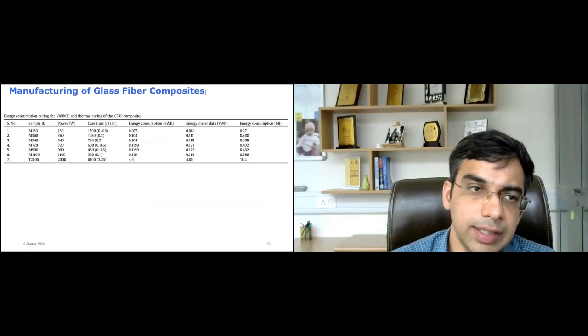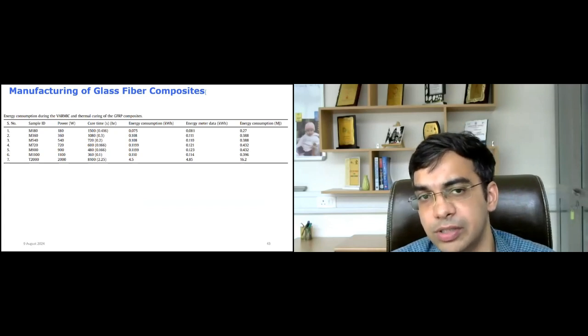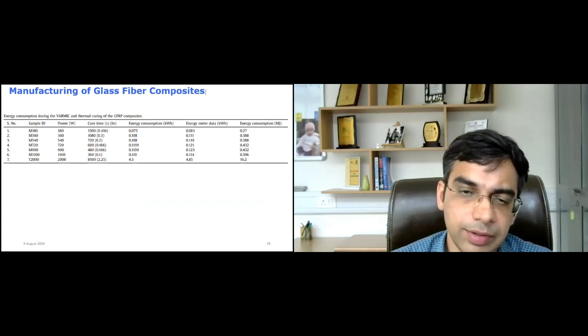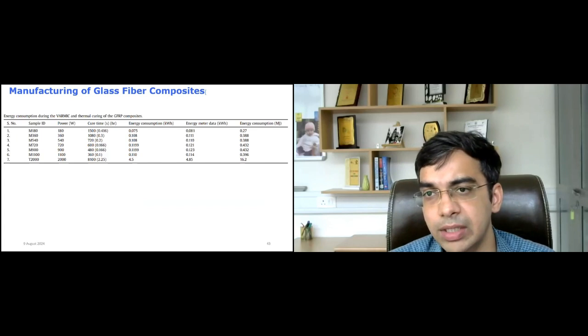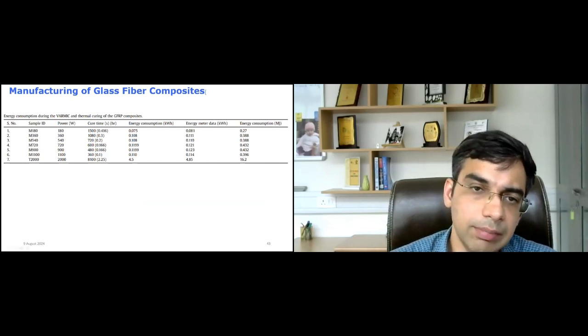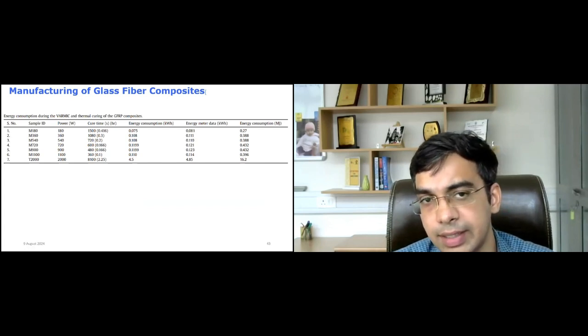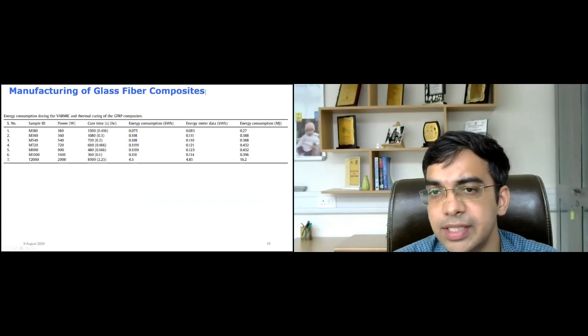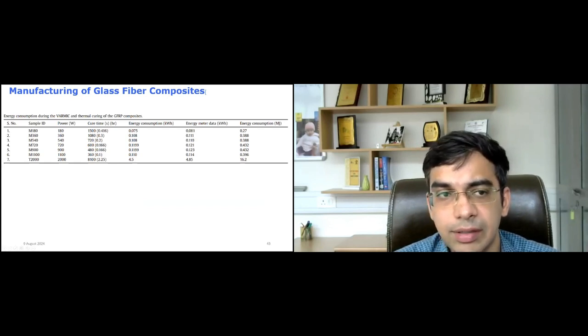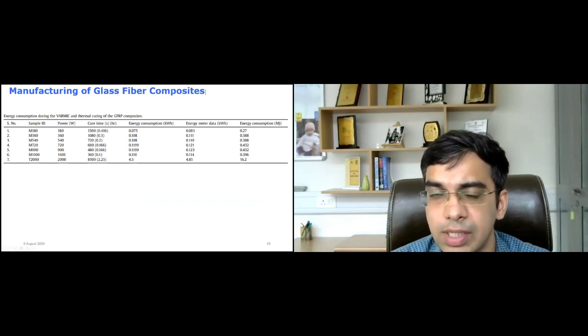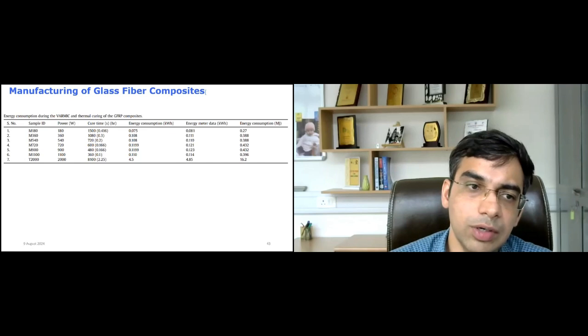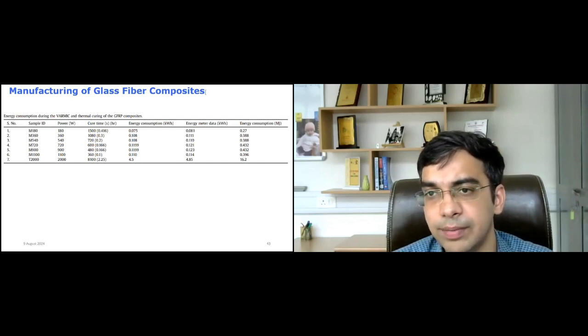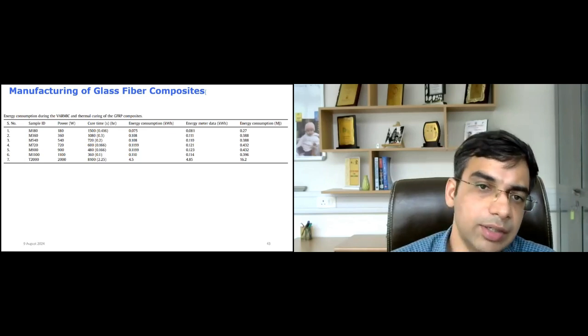So next we estimated the energy consumption during the manufacturing process, which is of interest to many industries. Of course this was done on a lab scale, but we installed the energy meter in series to both the applicators, that is the microwave as well as the other thermal based applicator. We calculated the energy consumption both theoretically, that is multiplying the power and the cycle time, as well as from the actual energy meter data. So here we can see that energy meter data with respect to microwave is not even crossing 1 kilowatt in our case, but it was almost 5 kilowatt for the same size of sample developed using thermal curing. So from here we can estimate that by utilizing microwave energy, we can not only save time but also save a lot on energy costs.